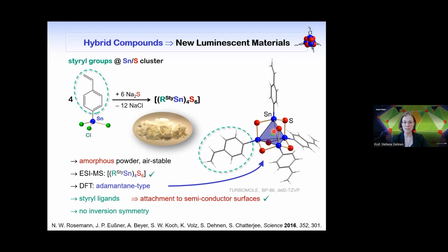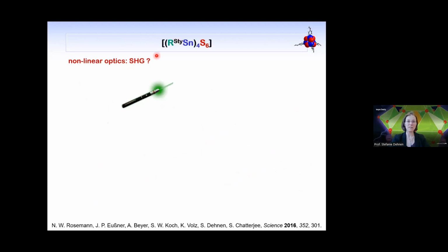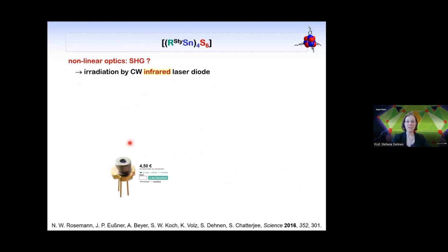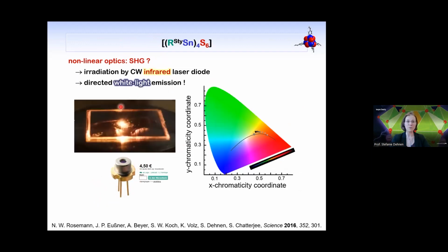This caught our interest, since no inversion symmetry in turn means that it can have nonlinear optical properties. So what we did is that we checked this, and what we expected was second harmonic generation. This is what you get if you have a laser pointer with green light: a red laser passes through an optical medium, and then you find the second harmonic being produced with the wavelength of green light. Well, actually, we did so. We used a CW infrared laser diode. We sent that through our powder, and what we got is not the second harmonic, but a broad spectrum. We got a white light emission.